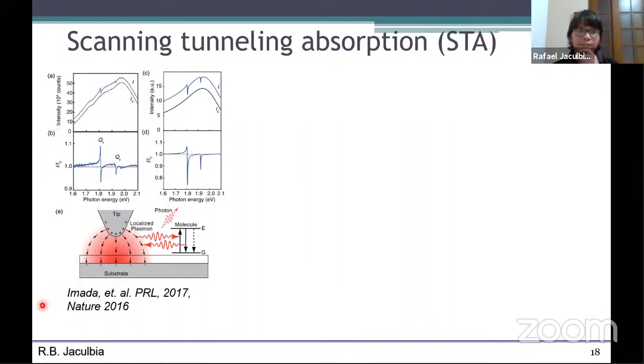So basically, Imada-san, one of our group members, used this light as the light source for absorption measurements. He found that when the tip is near the molecule, there were some dips in the scanning tunneling luminescence spectrum, and no dips when the tip is far. When you divide these two signals, he was able to get this. Through calculations, they found that these two features correspond to the absorption of the molecule. So it's one of the first demonstrations of single molecule absorption.